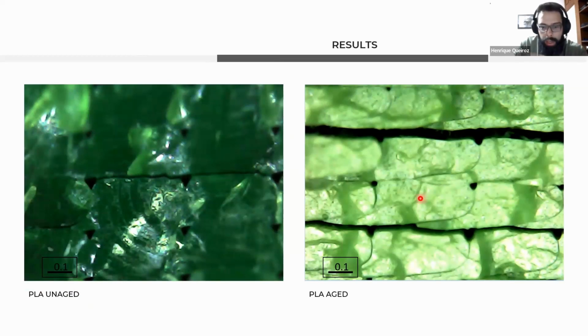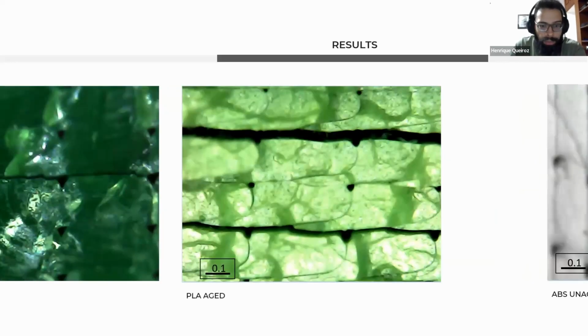But when you look at the aged specimen, these voids of the printed spaces are still there, of course, and they acted as the capillary ways where the water got in and started accumulating in these small fractures. And as time goes on, more water is in there, and it starts to debond the layers, which is the reason why the mechanical properties tend to go down more significantly for PLA than for ABS.